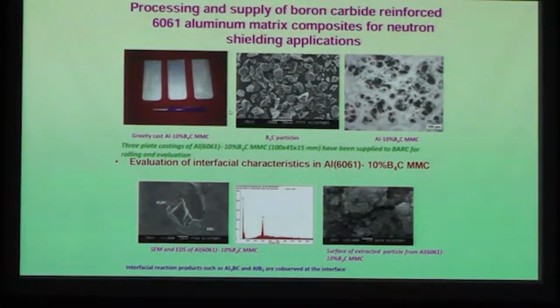We also work on neutron shielding materials with BARC, but here the requirement is that the boron carbide particles have the neutron shielding capacity. So we incorporate these particles in the aluminum matrix, and these are being made into panels. These panels are used as containers for transporting spent fuel from the nuclear reactors to other sites, dumping sites or preserving sites and so on. So there we develop some of the materials and supply to BARC.